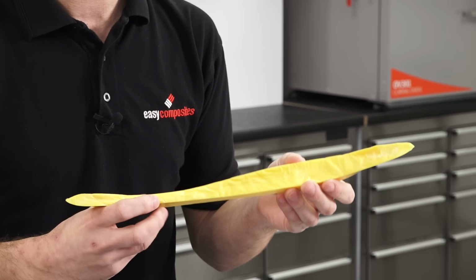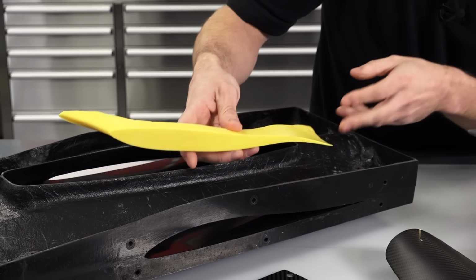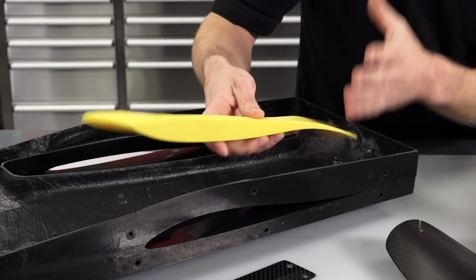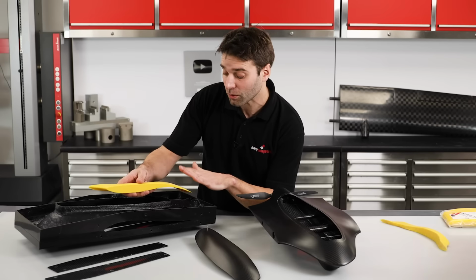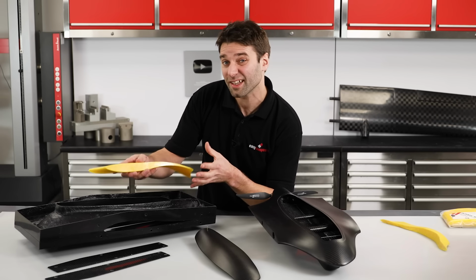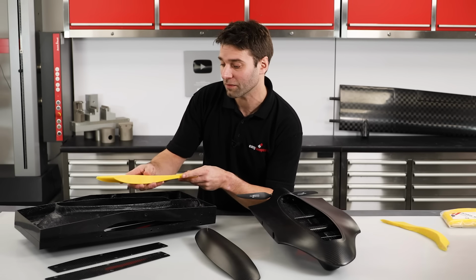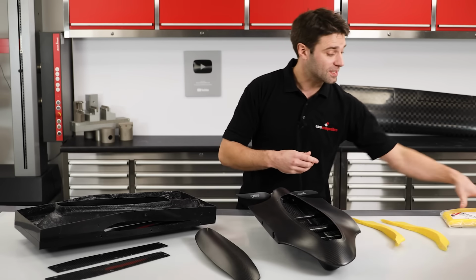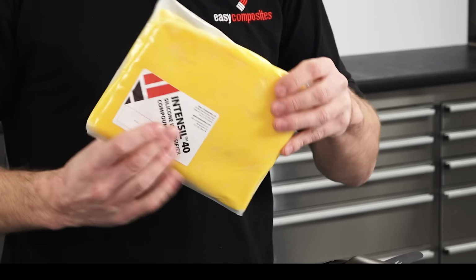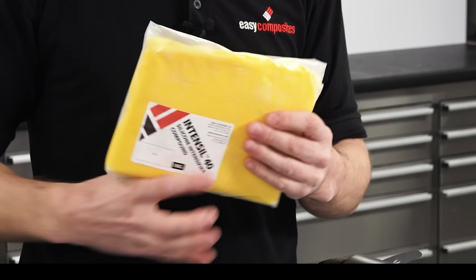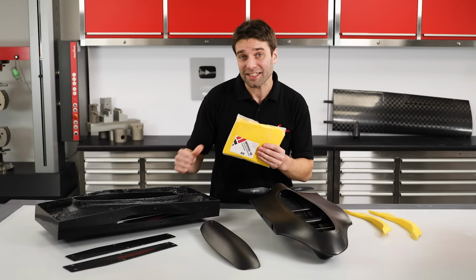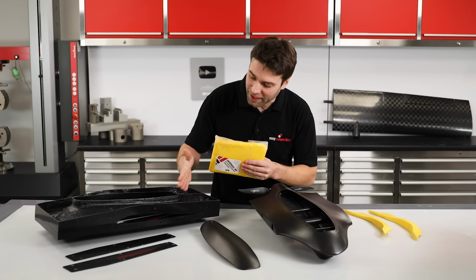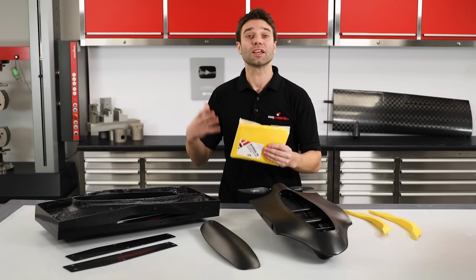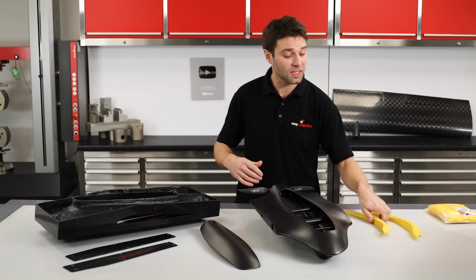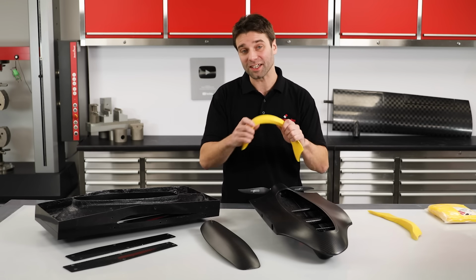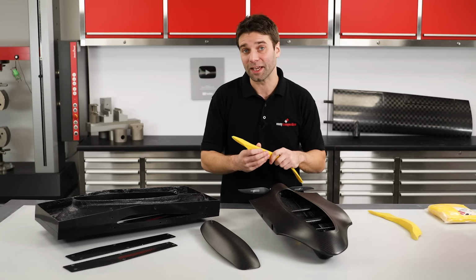These are silicone intensifiers. So they're a rubber insert that get installed into these complicated areas and allow consolidation into those detailed bits where the bag wouldn't normally follow. In its uncured state, it's a very soft and pliable material, not that dissimilar to a modelling clay, and it's used by pressing down into any of those complex and detailed areas. Then it's cured under heat, and that forms these flexible rubber inserts that can be reused indefinitely.